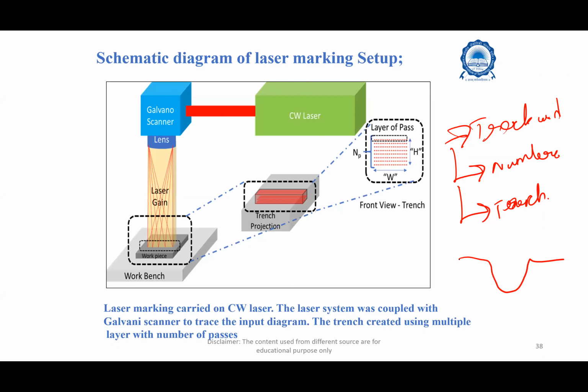If this is my surface, I get a Gaussian beam profile in the form of a shallow groove at the center of the bottom, with more depth at the sides. These TEM modes allow the concentration of lower energy at the center of the beam and more energy at the edges. So the roughness profile reduced with an increase in the number of laser passes due to the consistent impact of the laser beam irradiation and the rapid vaporization of the material.